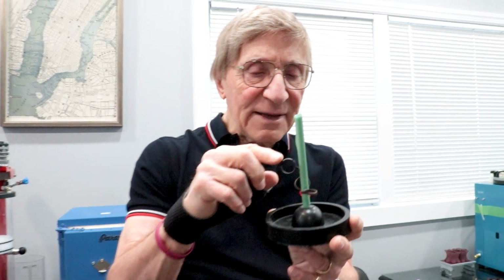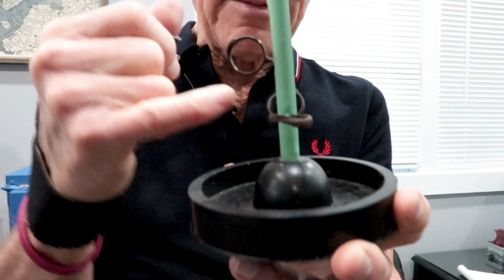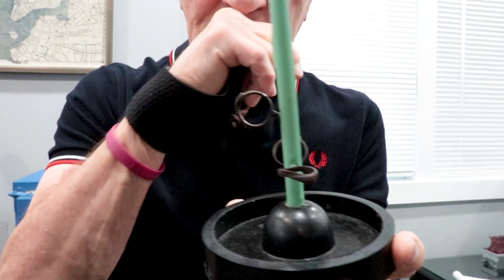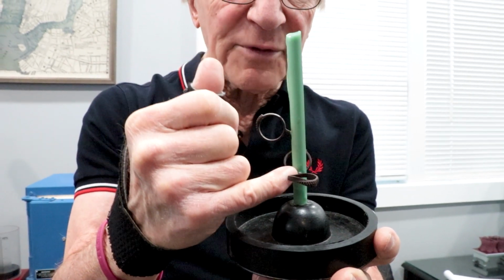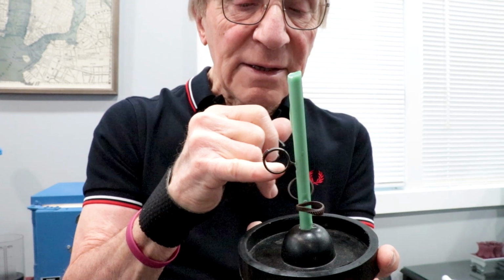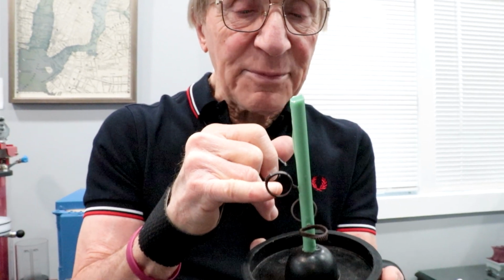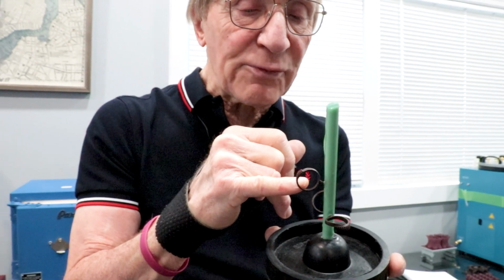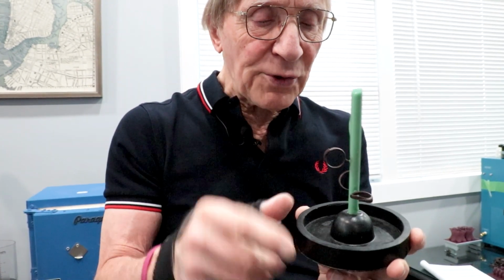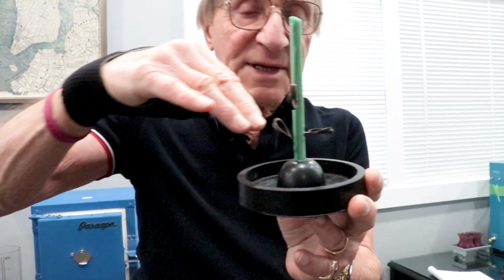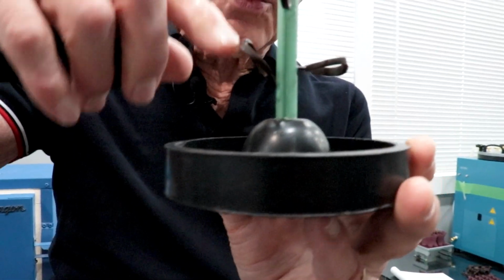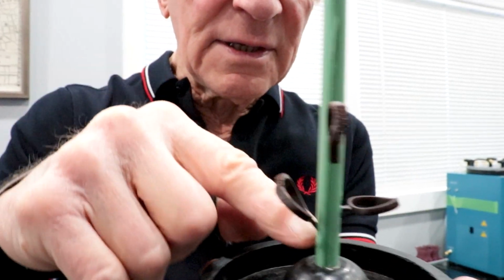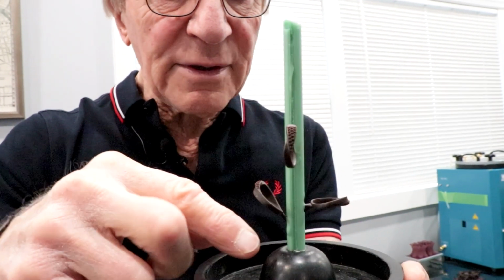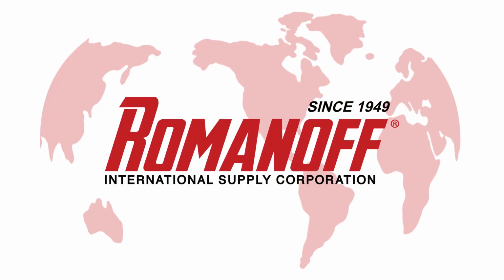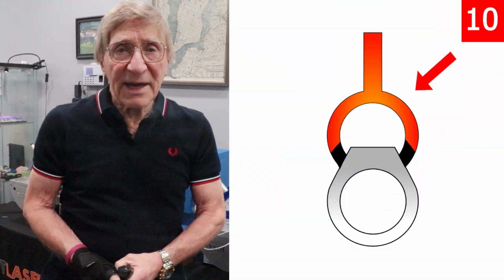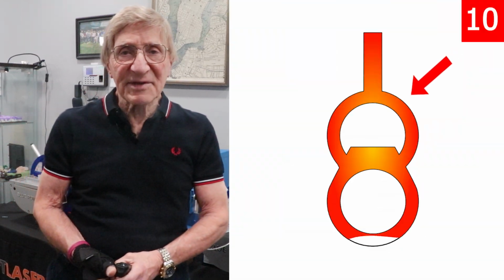Also, you have to be careful. If you put the ring like this because you think you're saving space, the problem here is that the lower half of the ring over here cannot drain out from the tree, and also the surface over here will go very high in temperature, boil, and also cause a rough surface in the casting. So the only correct way to put pieces on a tree is that they be on a 45-degree angle so the wax can drain out very easily to the tree trunk, and from the tree trunk to the base, and so on.